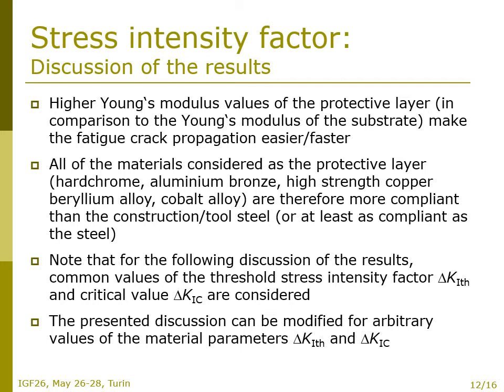Higher Young's modulus values of the protective layer in comparison to the Young's modulus of the substrate make the fatigue crack propagation easier or faster, let's say. All of the materials considered as the protective layer, hard chrome, aluminum bronze, high-strength copper beryllium alloy, or cobalt alloy, are therefore more compliant than the construction or tool steel, or at least as compliant as the steel. Note that for the following discussion of the results, common values of the threshold stress intensity factor delta K1TH and critical value delta K1C are considered. The presented discussion can be then modified for arbitrary values of these material parameters.